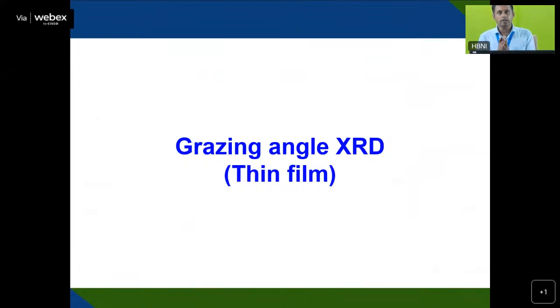In addition to single crystal, there is another technique, powder XRD, which mostly uses powder samples. In single crystal, you are using optically transparent material, mainly single crystals. But if you have a thin film, that is not possible in single crystal, nor in conventional normal XRD. Normal XRD works if the thin film is a little bit thick, but if it is quite fine, like a nano layer or micron size, it's difficult to see by normal powder XRD.